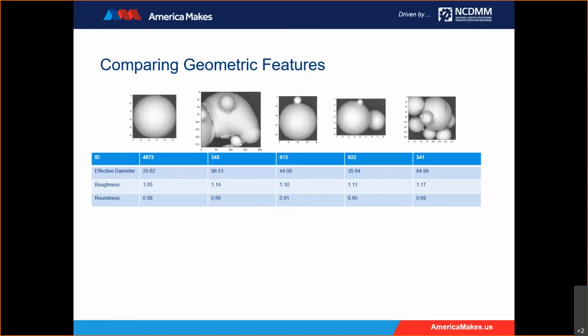Satellite particles are problematic for the AM powder process because they prevent the smooth flowability and uniform powder distribution on the powder bed by the recoater in laser powder bed fusion methods, for example. Satellites are typically generated during powder fabrication by gas atomization. They're also generated during the printing process when the powder is exposed to thermal cycling. They typically show higher surface roughness and aspect ratio than, for example, virgin particles.